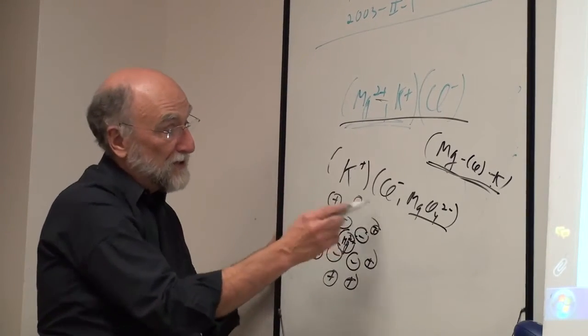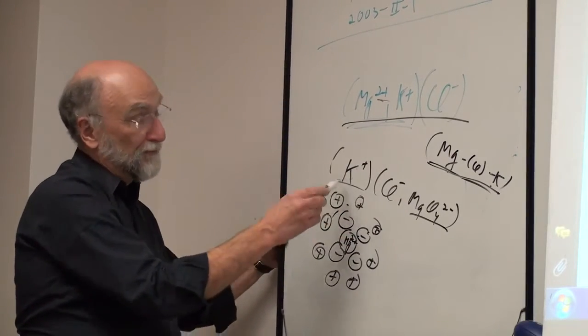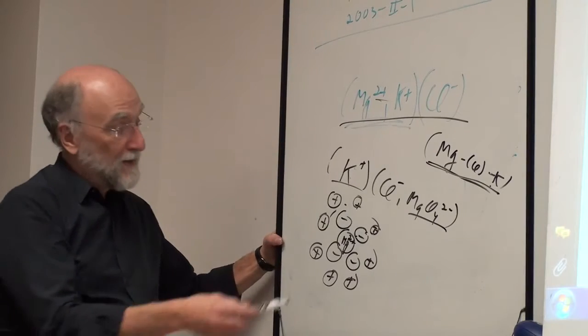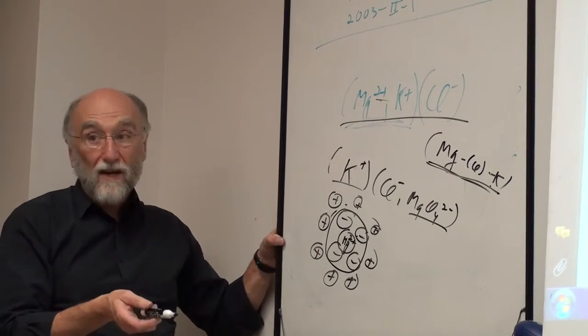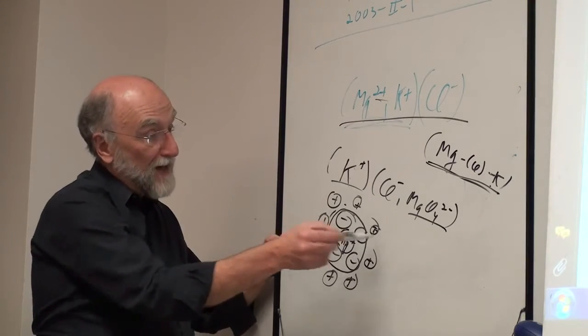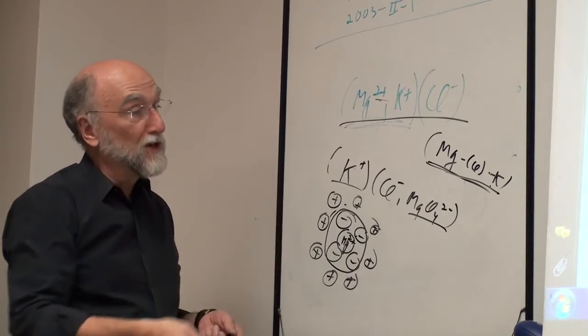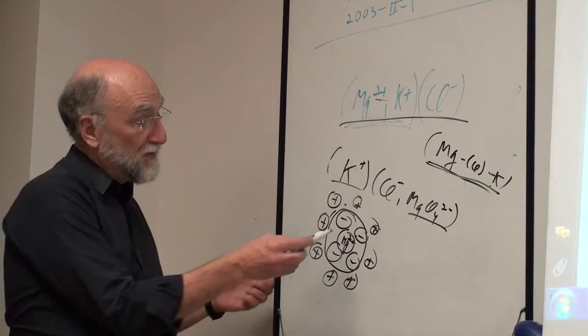Now imagine this situation in a system that's very rich in potassium: this MgCl4 could be considered a complex anion unit. If you treat this as a separate entity mixing on an anion lattice with the chlorines, you can work out the mathematics, and you get almost the same model.